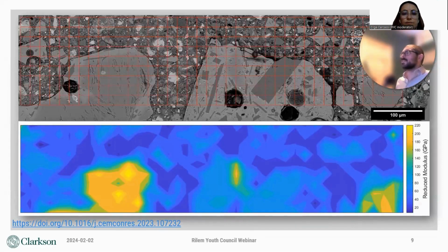We wanted to learn about the strength of the material, but it's very expensive to send samples to the space station, so the samples we send are far too small to perform any mechanical tests. So we do something called nanoindentation, which is when we take a microscopic probe and indent the surface along a grid pattern to see how hard and stiff the material is at that location. This helps us understand the strength of the particles within the microstructure, which we can then feed into a numerical model that might help predict the structural scale properties.